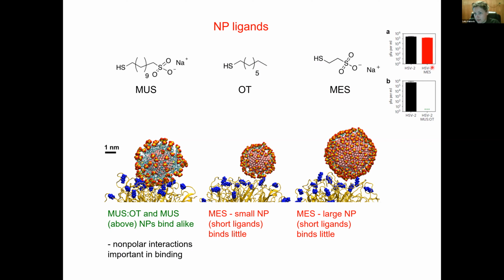When it came to these other ligands, such as MES, that we also tested experimentally and that didn't show antiviral activity, we found that because the ligands were so short, they couldn't make many interactions with the virus proteins. They were basically very rigid spheres, these nanoparticles with short ligands. So the length of the chain definitely played a big role, and also having ligand chains that can exhibit nonpolar interactions was an important part of the mechanism.